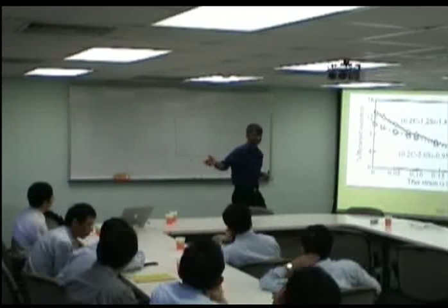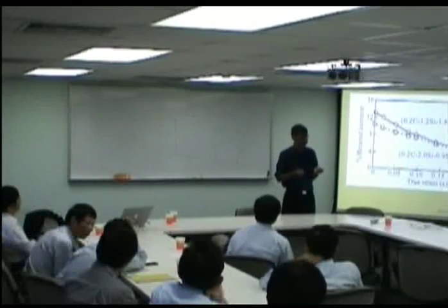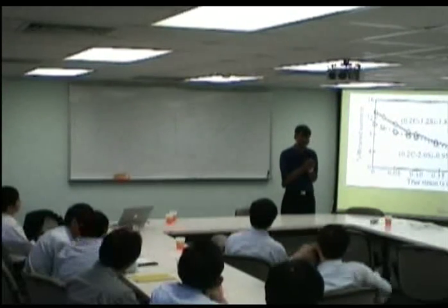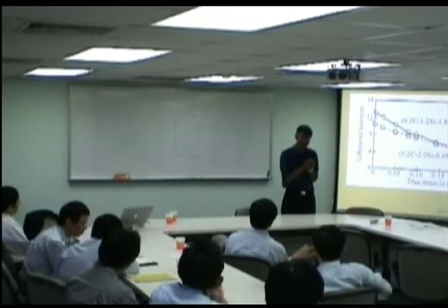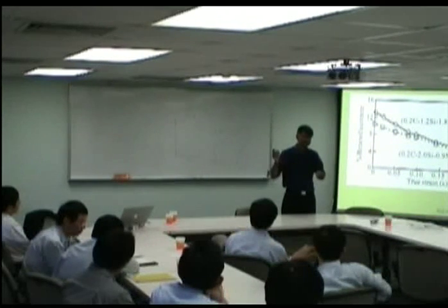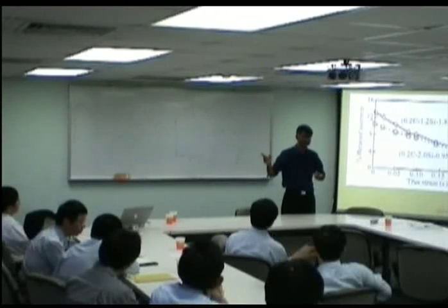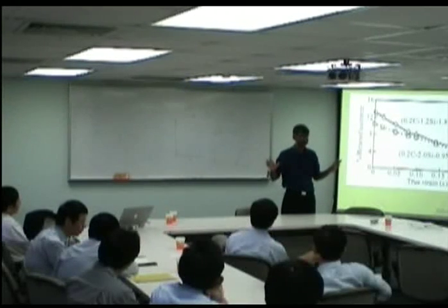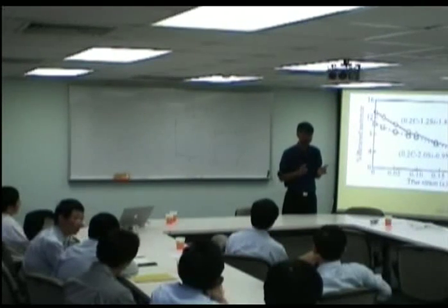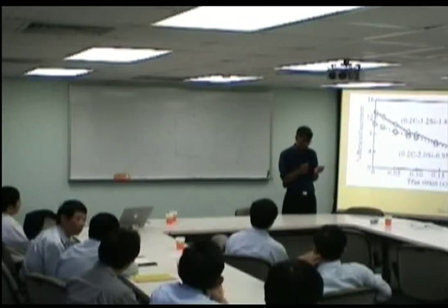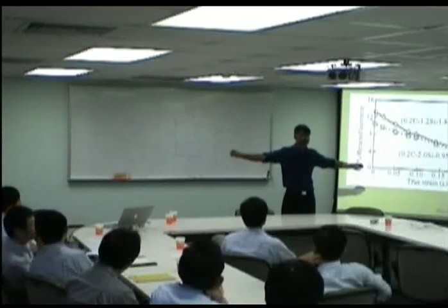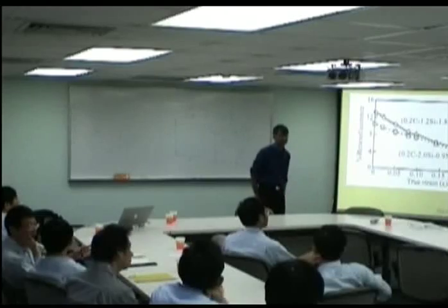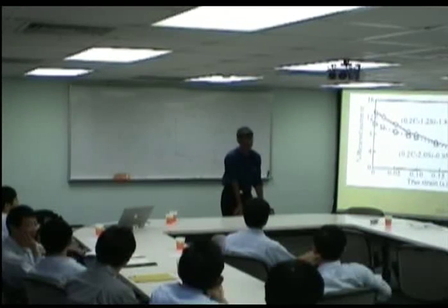Now, one or two days ago, Professor Yang did some experiments in which he took austenite and deformed it to a true strain of 6.6. That's a huge elongation, and he still didn't manage to transform the austenite to martensite. So he only obtained 50% martensite in austenite. The rest of it remained as austenite, even after a true strain of 6.6. So that's like taking a piece of steel about this big and stretching it to 1 kilometer, and it couldn't transform the austenite. So I was very amazed to see those results.